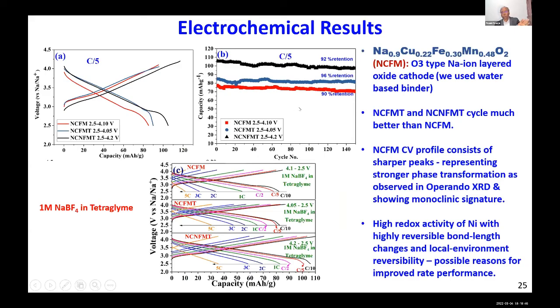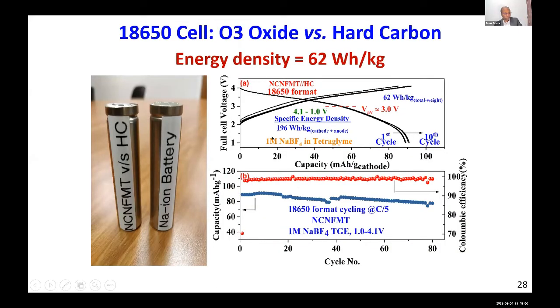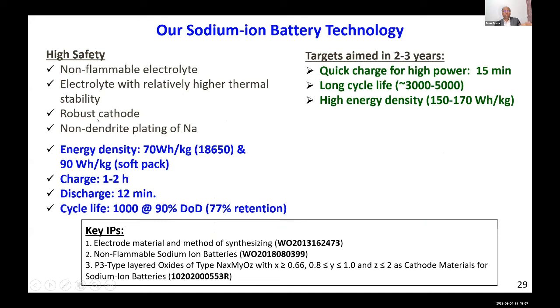And then we have also shown a full cell performance. I'm going to skip because of lack of time. So the message here is our sodium ion cell uses non-flammable electrolyte, and it does not have dendrite growth. That's the most important thing. No dendrite growth.